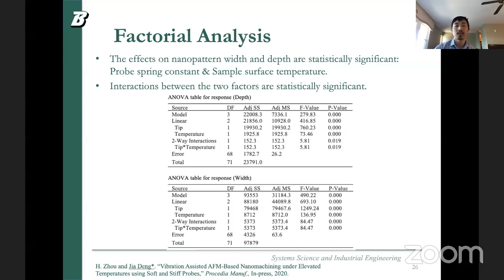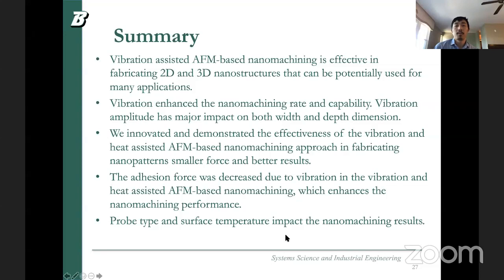So we did the factorial analysis of this. We can clearly see there are statistically significant results for the cantilever type and the temperature, and it is also statistically significant for the interaction between the tip and the temperature. That means if we choose another tip, the temperature selection is affected. If you want to see more, you can find more results in Procedia Manufacturing.